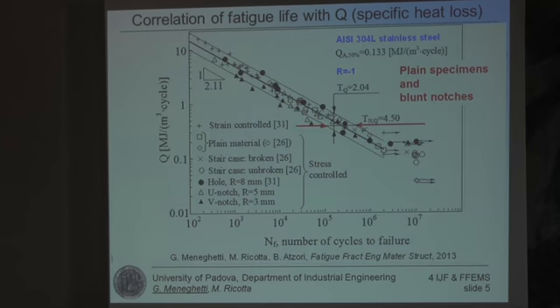But if we plot this data all together using the heat energy released as heat, you see that all the data collapse into a single scatter band, which has a scattering index more or less equal to that of a single test series. So we can say that the heat energy could correlate with fatigue lives. Now, we have no cracked specimens here, only smooth and bluntly notched specimens. The reason why I am showing you this figure is because we will use this figure later on. So we have this energy synthesis at a load ratio equal to -1 for our material.